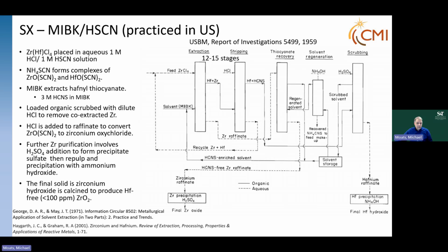And then the zirconium, which is now a zirconium chloride, comes around and is precipitated with a sulfuric acid matrix, then repulped with an ammonia solution to finally lead to a zirconium oxide after calcination. This zirconium is less than 100 parts per million hafnium, which is considered hafnium-free by the nuclear industry.